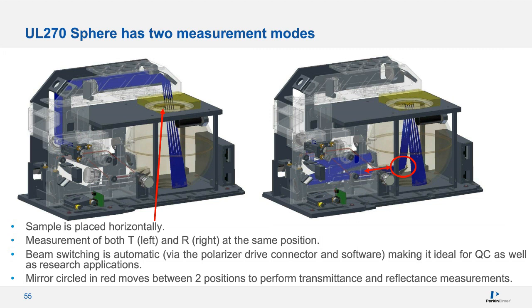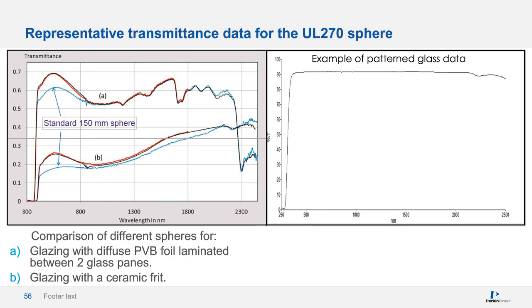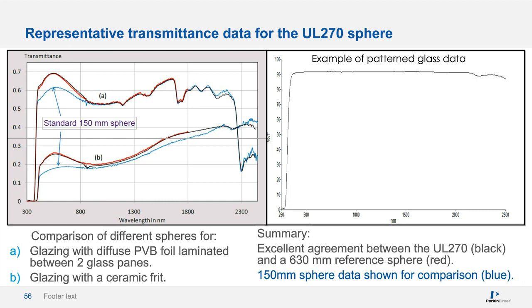So here is some data for the 270mm sphere. In this case, we are comparing the sphere with data from a much larger 630mm sphere based at the Fraunhofer Institute in Germany. We see excellent agreement between the 270mm sphere and the much larger 630mm sphere. In contrast, the 150mm integrating sphere in blue falls short in providing accurate data within the visible range. This would have major consequences for window and building design considerations.